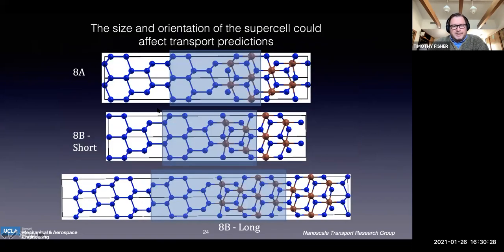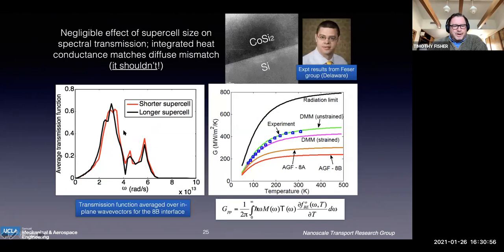I think that this is an important result. So the size gets back to that superlattice size, right? So we have short and long. And the longer you go, the more computer time it takes, and then your students who are running the simulation start to ask questions like, how many decades is it going to take me to get my PhD, and those sorts of questions come up, and so it's a compromise. And what we did is we saw, at least in looking at the transmission function, that's the important thing again in the Landauer setup, that the shorter and longer supercells were reasonably close. And then Joe Feser, he made a really nice cobalt silicide silicon interface for us. And we ended up getting experimental data.